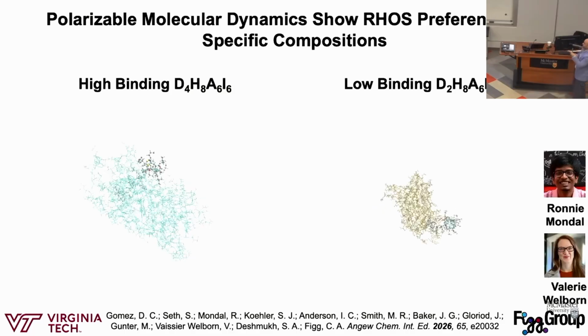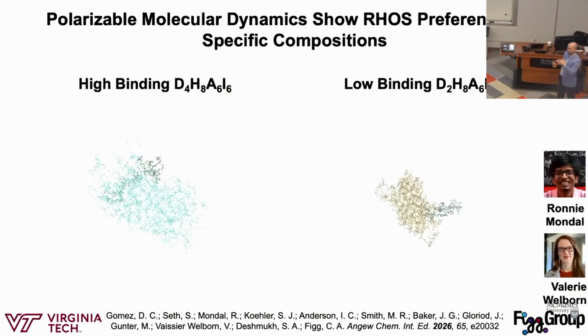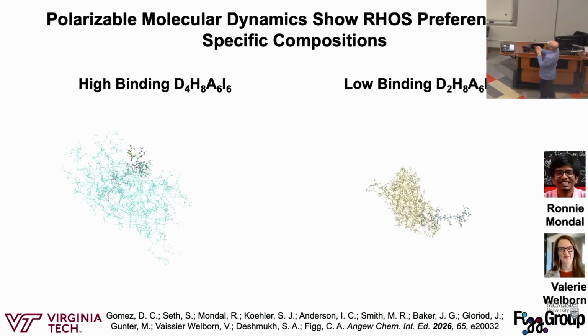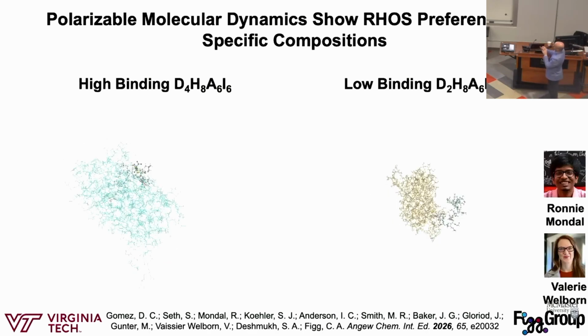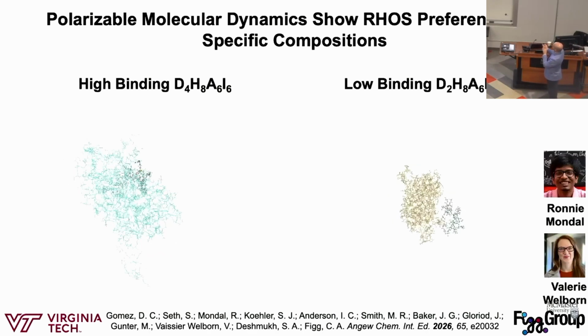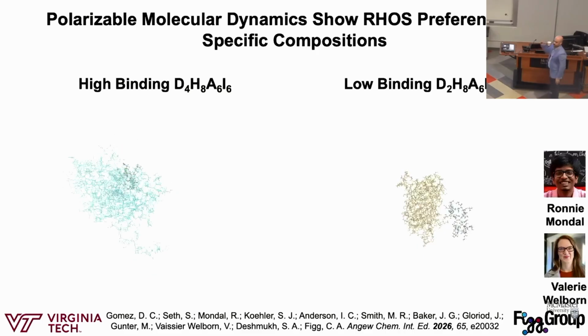These are 100 nanosecond simulations. They take about a month and a half to run. What you see is that the high binder stays around the barrel and is mostly interacting in the same site, whereas the low binder is going to fly off and not interact with the protein again.